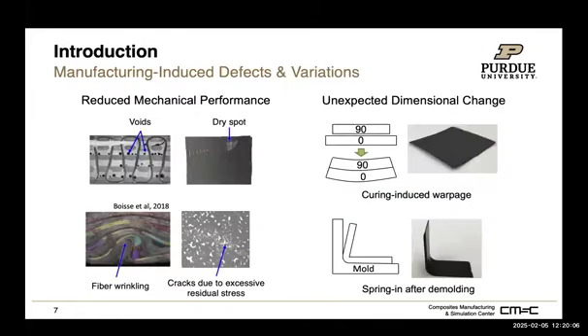So because of this manufacturing process, beyond the advantages of using composites, we also see defects. Those defects can come from the infusion process, where you can see dry spots, which means the resin or the polymer never reached that area. So there can be something wrong with the infusion process. There are cases when we do the forming of those dry fibers where wrinkles can occur, especially when the geometry of the mold is very complex.